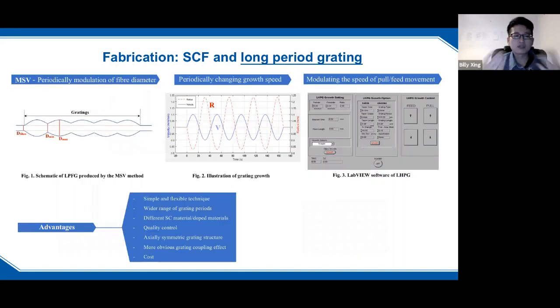In our proposed method, we achieve fabrication of the grating by periodically modulating the fiber diameter. Here is a schematic of the long period grating produced. This was achieved by changing the growth speed periodically. When we increase the pull rate speed, the fiber diameter decreases. When we lower the speed of the growth, the diameter of the fiber becomes larger. As you can see in this picture, the red dotted line is the radius of the fiber, and the blue line is the speed of the pull rate. So our pull rate and growth speed go up and down in that pattern, and the grating can be grown.